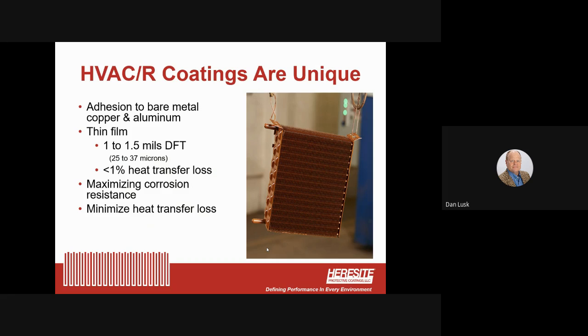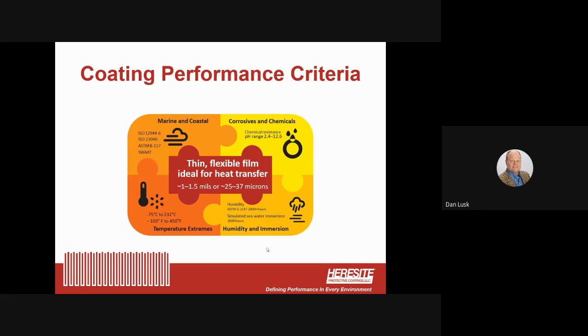And the reason they go on so thin is to minimize heat transfer loss, so that you get the same performance of the heat exchanger with the coating on and without. So there's less than 1% heat transfer loss in using our coatings and protecting a heat exchanger. So really, these coatings have to do a lot in both marine coastal environments, in corrosive chemical environments, in temperature extremes, and both with humidity and with immersion. And really have to do a lot for a thin film flexible coating that goes on very thin.